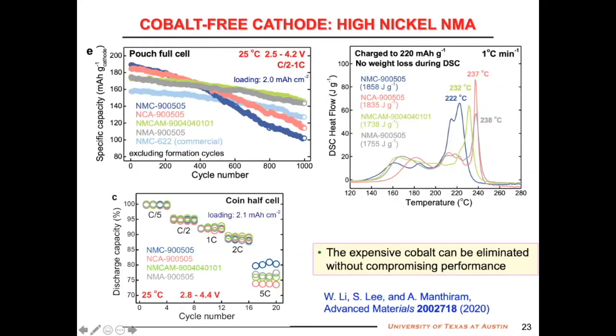So the ultimate goal is to eliminate cobalt completely. We have been successful in completely removing cobalt with 90% nickel, 5% manganese, 5% aluminum. That just came out in Advanced Materials last week. So we are comparing a series of compounds here. Only NMA here does not have any cobalt. Others have a little bit of, 5%, cobalt.